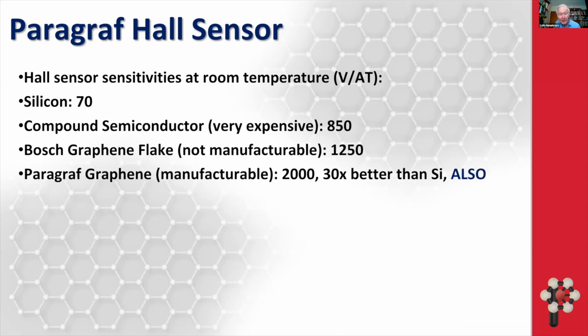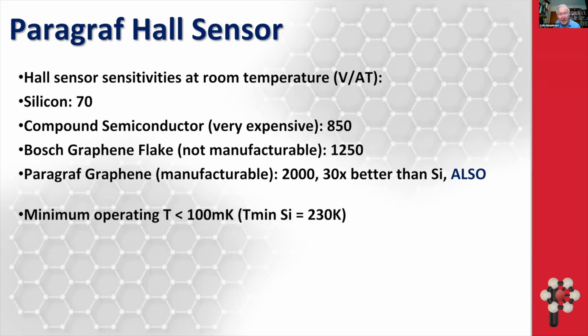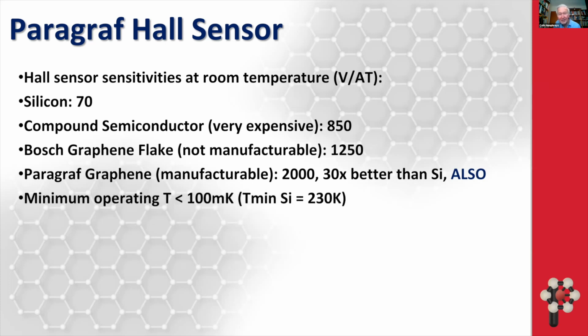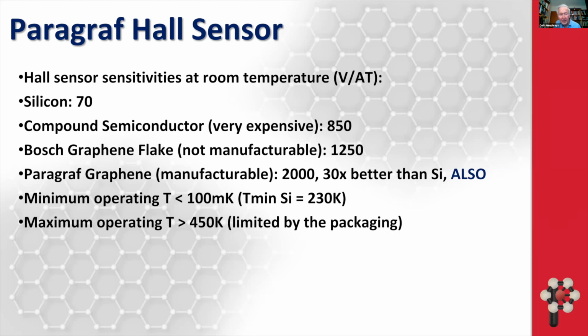A Paragraf graphene Hall sensor, 2,000 volts per amp Tesla. So it's 30 times better than silicon. So we have replaced silicon in this device. And also it can do things a silicon Hall sensor cannot do. Our Hall sensor operates at 100 millikelvin or less, so it's a cryogenic operation you can do as well as room temperature. The minimum you can get with a silicon Hall sensor is 230 K. Our maximum operation temperature is 450 K at the moment.